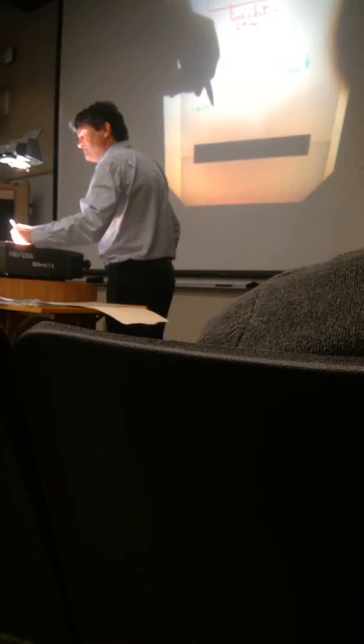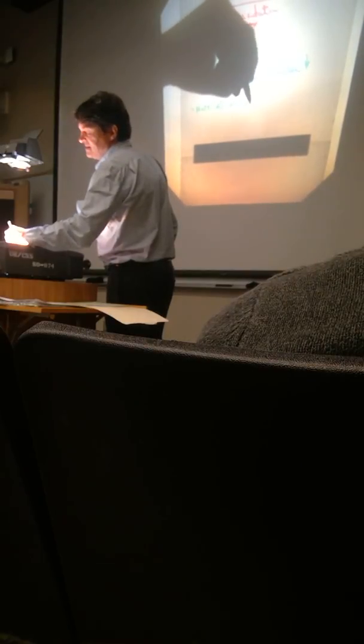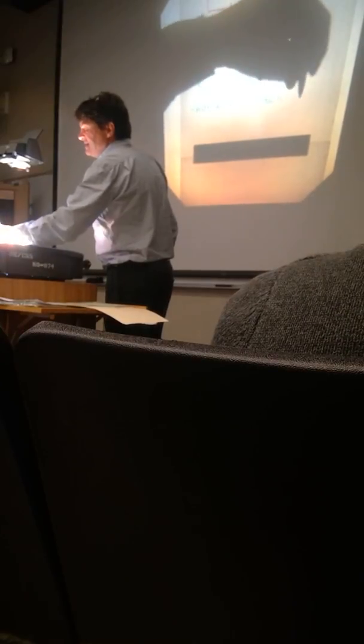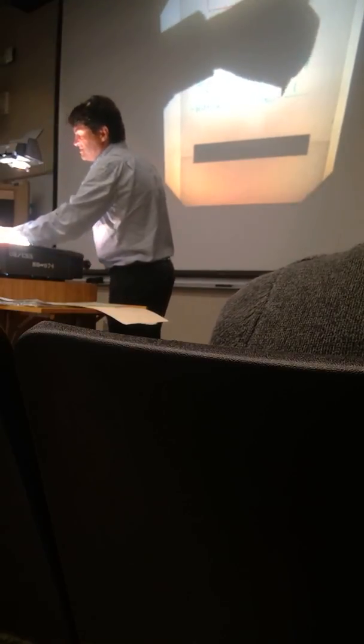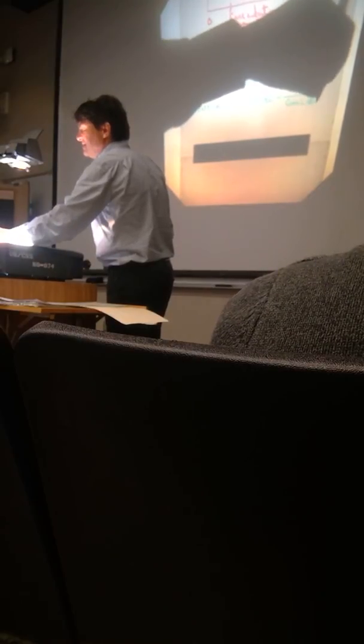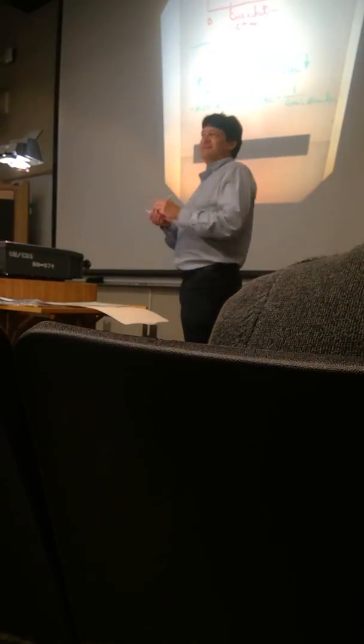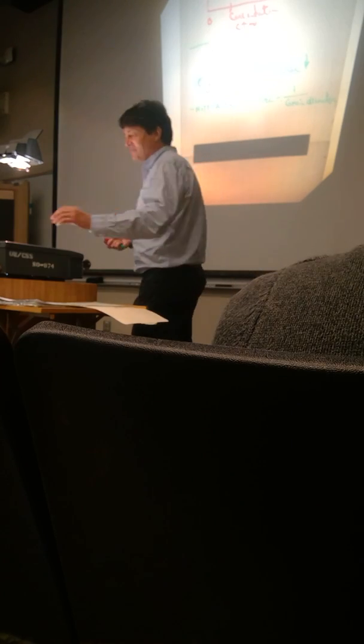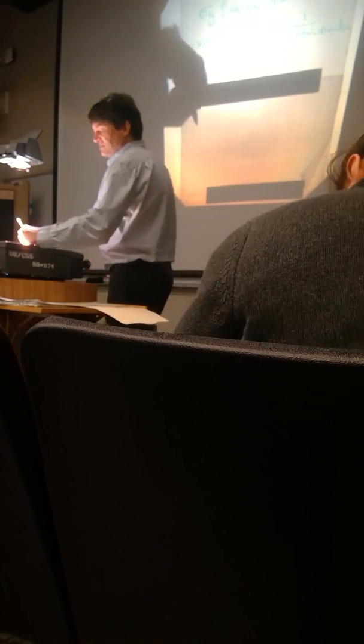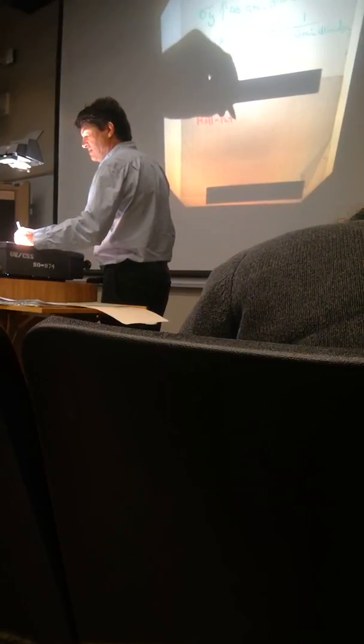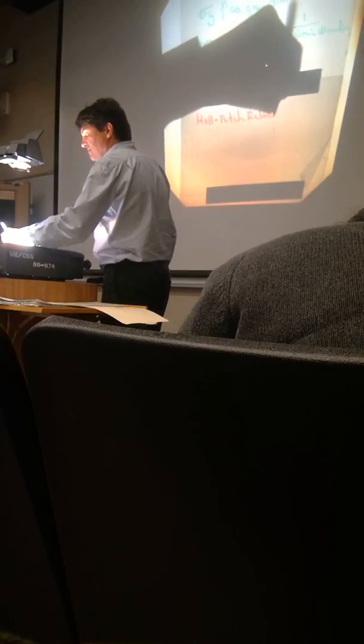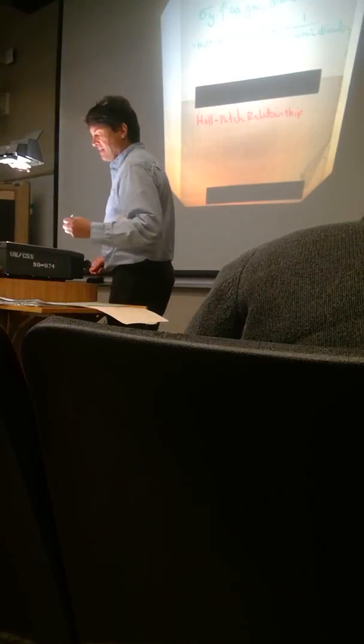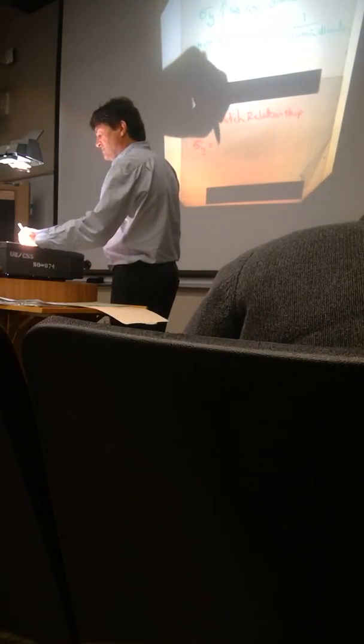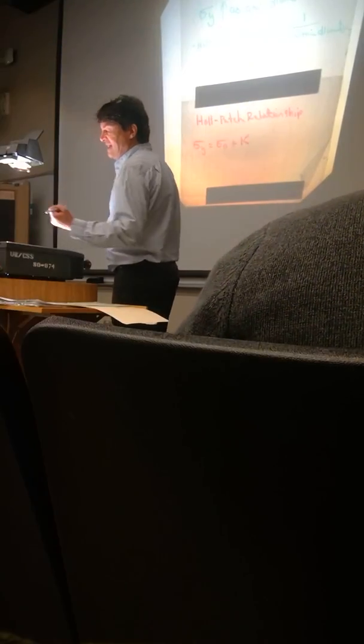So just note ASTM grain size is proportional, I should say, not exactly this, proportional to 1 over grain diameter. But in this class, when I say grain size, I'm talking about grain diameters. And this is what we call the Hall-Petch relationship, where sigma yield is equal to sigma naught plus some factor K of the material times D to the minus 1/2.